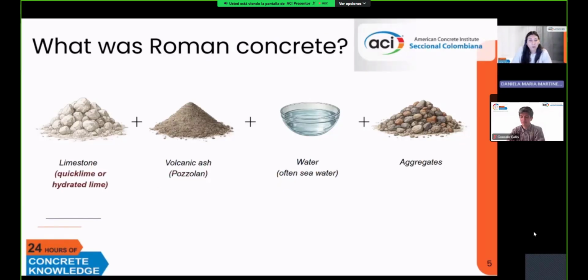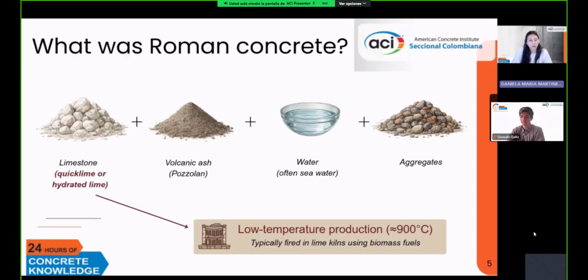So like I mentioned before, limestone first was heat treated to obtain calcium oxide or quicklime or hydrated lime, depending on the mechanism. But limestone had to be first calcined in some ancient Roman kilns that were typically fired with biomass fuels. These biomass fuels were usually just wood that they had in the surrounding areas. And in order to obtain quicklime, the kilns were fueled to lower temperatures, usually 900 degrees Celsius, more or less.